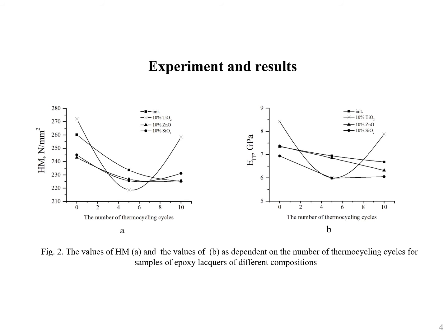The values of Martens hardness and the normal elastic modulus for the unmodified lacquer coating decrease smoothly with the increasing number of thermocycling cycles. Thus, hardness decreases by 10% after 5 cycles and by 14% after 10 cycles from the initial hardness value. In turn, modulus decreases first by 5% and then by 10% from the value of the modulus corresponding to the material not subjected to thermocycling.